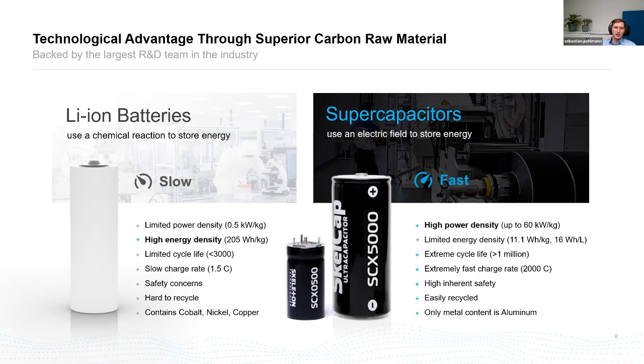Also, cycle life, for example, since in lithium-ion batteries you have two materials that are basically used as a shelf for energy storage. So you always put something in, you take it out again. This is a wear and tear on materials, which means that you have limited cycle life. Today's lithium-ion batteries, depending on which chemistry you use, have around 3,000 cycles. Some of them have 5,000, 10,000, even 20,000 cycles. But compared to supercapacitors, there's barely anything, because you have way over 1 million cycles with supercapacitors, and in industrial devices, easily 2, 3, 4 million cycles.